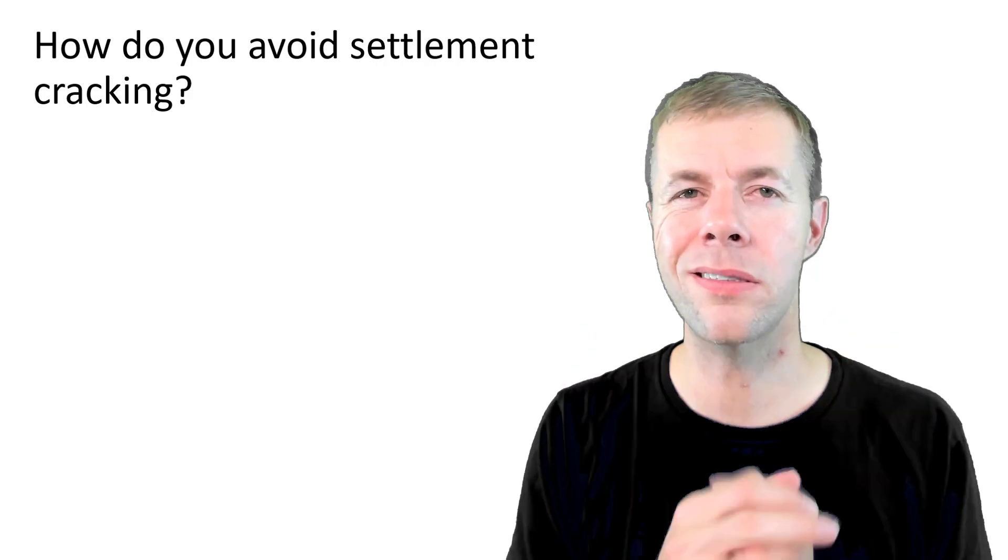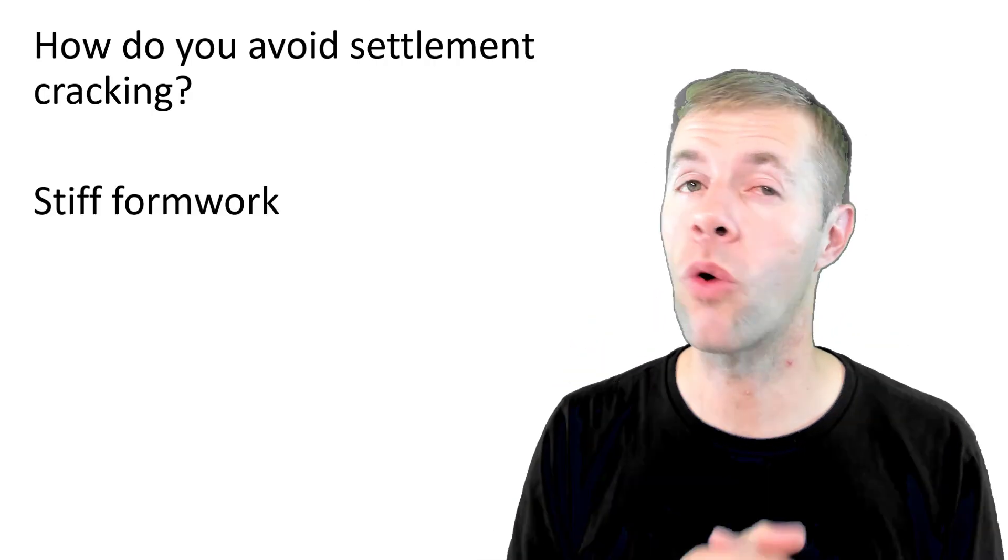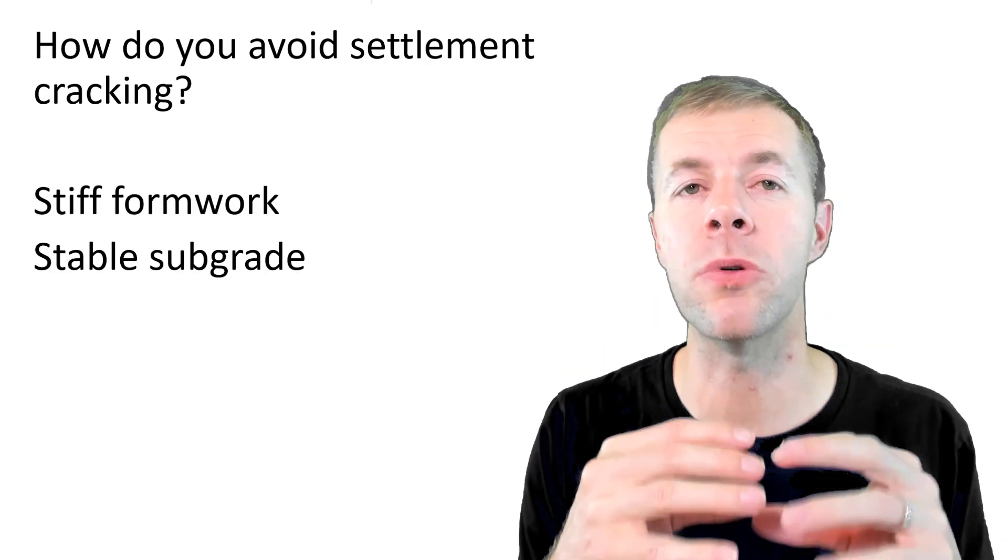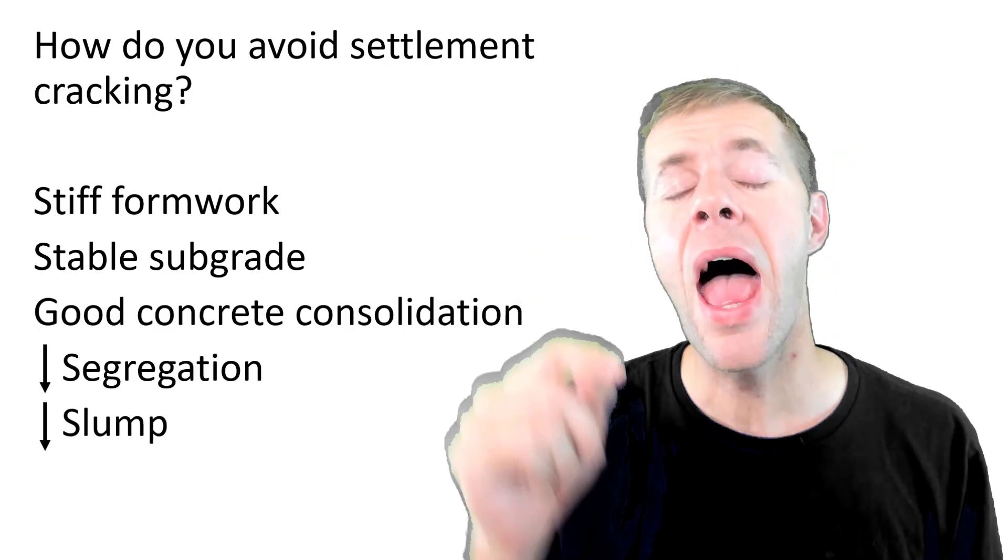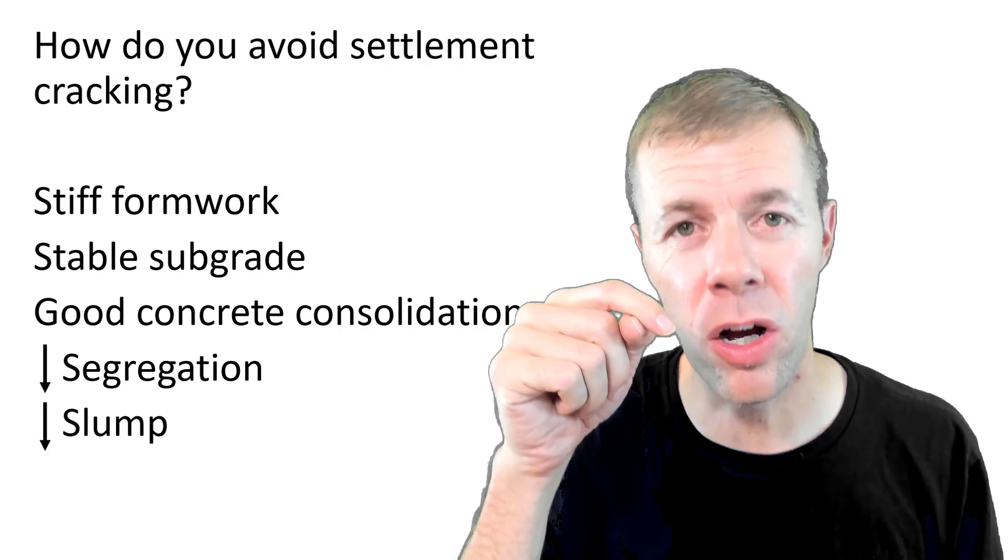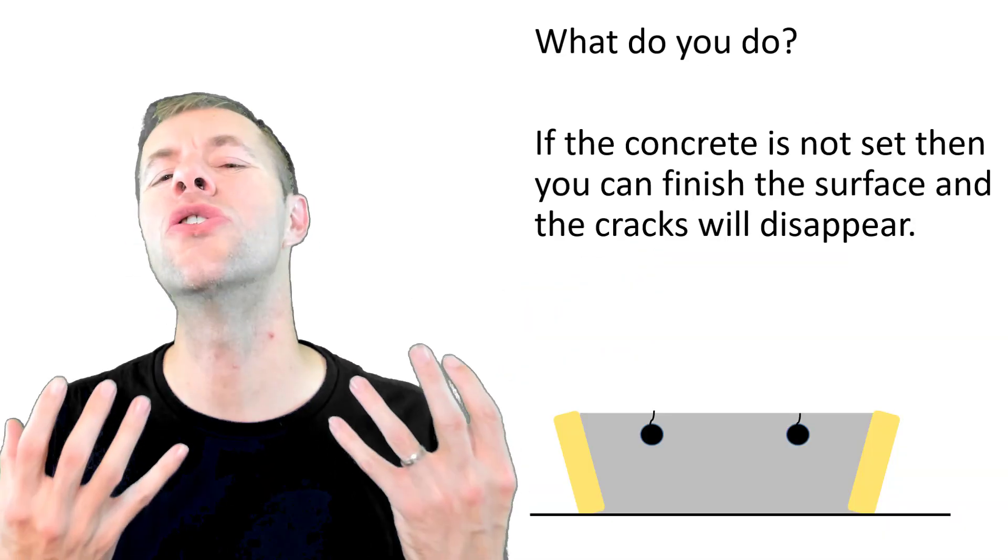So how do you avoid this? You can have very stiff formwork, a very stable subgrade, good concrete consolidation, low amounts of segregation, and lower amounts of slump.